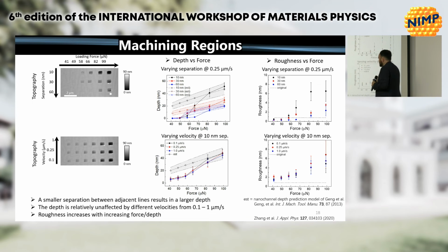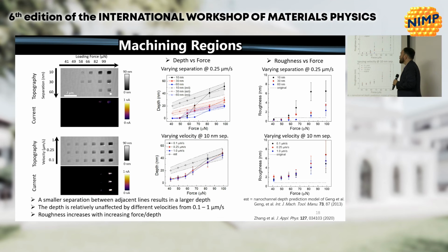We tried fitting it to some existing models, but the models don't take into account the presence of removed material or whether there's a structural phase change, as is the case when you're applying micronewtons of force. For very low forces, you can see that the roughness is on the same level as the roughness of the film initially. And again, velocity doesn't play a very strong role in the range that we looked at.